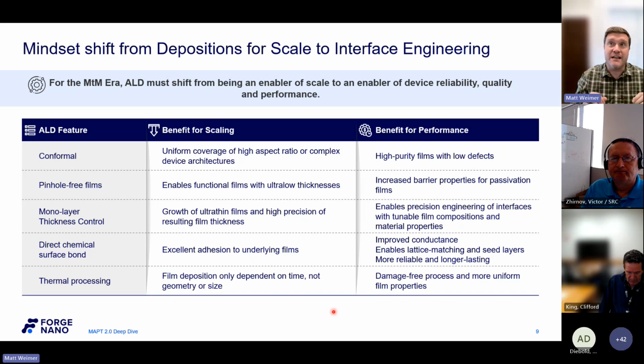Another thing to consider is a lot of wafer flows have some etch process before you get to your deposition process. That can leave behind residues that don't matter for PECVD, but will matter for ALD. If you think about leaving behind some fluorocarbon, maybe even just a single monolayer on a trench, that will inhibit ALD growth because it doesn't want to bond to that necessarily. It wants to clean it out, and then it has to find the surface to bond to. So again, it really depends on the incoming surface, and also, of course, the features.